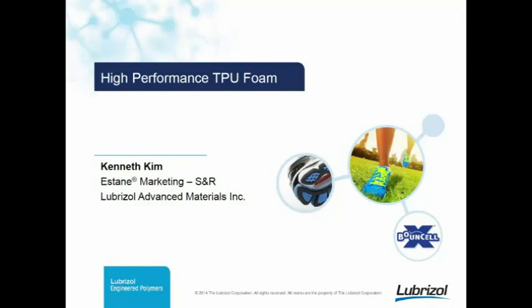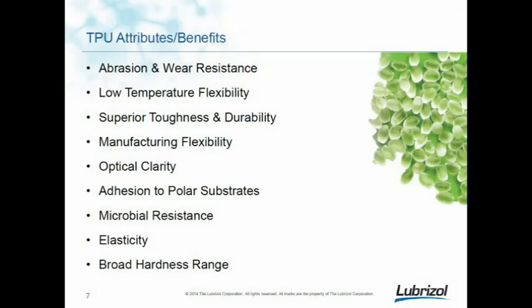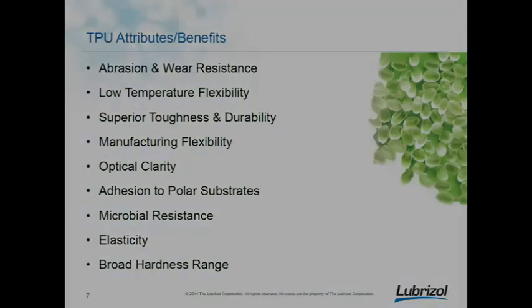Another innovative company producing unique polyurethane solutions for the footwear industry is Lubrizol, offering its new Estane-based TPU solutions through its Bouncell X microcellular TPU foam containing Lubrizol Estane TPU. Bouncell X benefits include lightweight, outstanding long-term cushioning, thin solid skin for durable TPU performance, hardness, and energy absorption return, high-efficiency injection molding process with over-molding feasibility, use of industrial regrind or post-consumer recycling possibility due to no cross-linking or chemical blowing agents in foaming process.